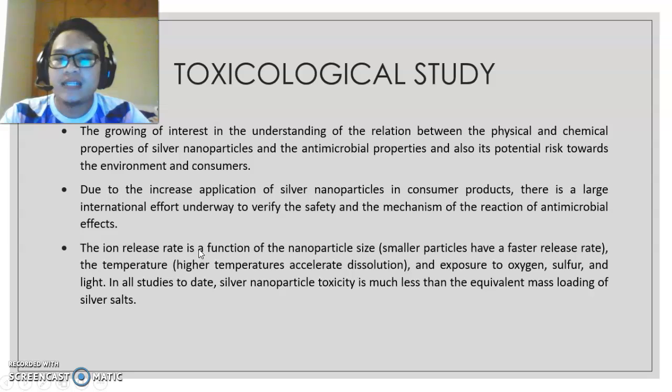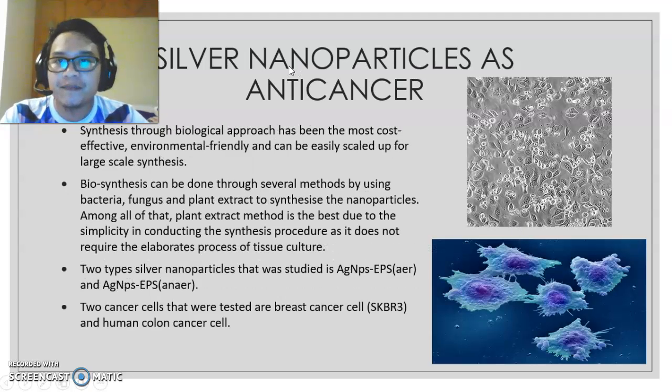The ion release rate is a function of the nanoparticle size, where smaller particles have a faster release rate. Higher temperatures accelerate dissolution, as do exposure to oxygen, sulfur, and light. In all studies to date, silver nanoparticle toxicity is much less than the equivalent mass loading of silver salts, which can be very beneficial since it may reduce the potential of causing side effects when used in the biomedical sector.